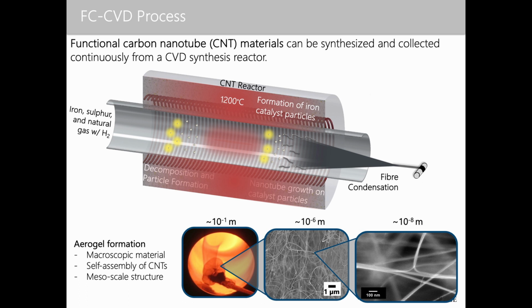So to tell you about the process as a whole, basically it is a high temperature reaction where one has a gas phase process, with hydrogen coming in. So the background gas is hydrogen. And then you have iron, sulfur, and natural gas or biogas, again, a form of methane that isn't so important as long as it's methane. And ultimately what you get is catalysts that form free-floating in the gas phase, at the relatively high temperature of this reactor, 1200 degrees C. 1200 degrees C in hydrogen is not something to take lightly, but nonetheless, many are running this.